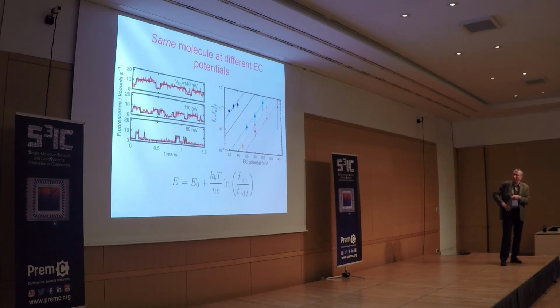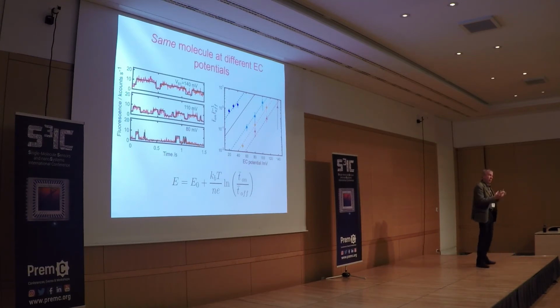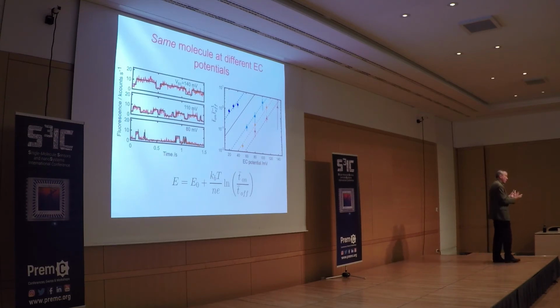Nowadays we could do better. This shows you that different molecules actually have different midpoint potentials. They react to the voltage in different ways. Why is that? The molecules are identical, of course, but what is different is that each molecule has a different environment on the surface. There are different charges. The ions in the glass or the impurities attached there will create a different local potential, and of course it will shift the midpoint potential, the equilibration between reduced and oxidized, differently depending on the molecules. That's what we see here.